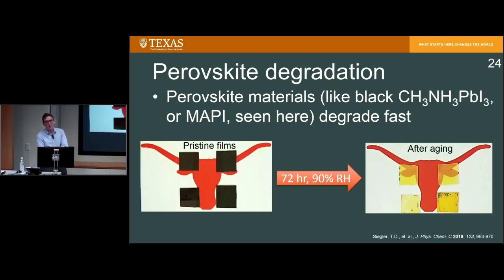To prove the point on the perovskite degradation, here are some photos I took before and after 72 hours of aging at 90% relative humidity for a recent paper I published. The perovskite films, when I first make them, are nice, dark black films that you can see here. But within only 3 days of aging, they turn into these useless yellow and white films of nothing.